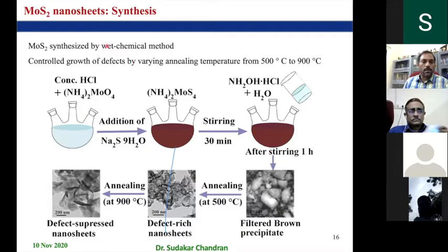So in this study, what we did, we prepared molybdenum disulfide using a chemical method. The procedure is typically shown here. This is a well-known procedure. At the end of this procedure, you get a brown precipitate, which you anneal at 500 degrees Celsius. You will get sheets. Typically, the sheets are around 200 to 500 nanometers in area, so they are very, very small. Of course, you can anneal at different temperatures under inert or slightly reducing ambient, so that it doesn't get oxidized. Under these conditions, you can alter the defect structure.